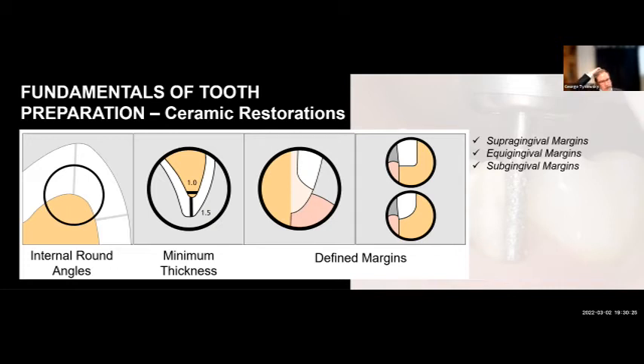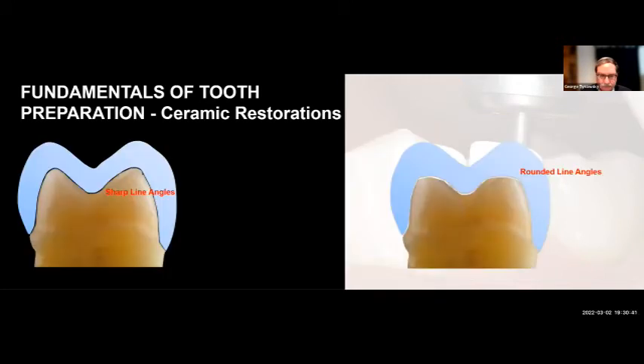When dealing with the 3Y, which is a very tough material, we can have more forgiveness and more of a traditional crown and bridge margin on those areas, because they can be milled down to about 0.5 with the 3Y material because of its strength and edge strength accordingly.